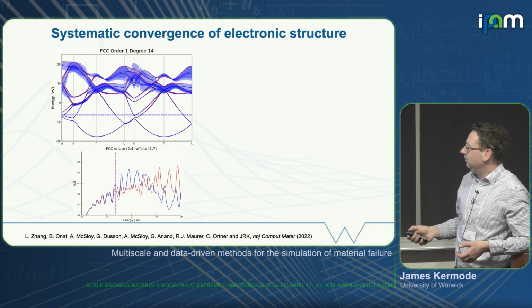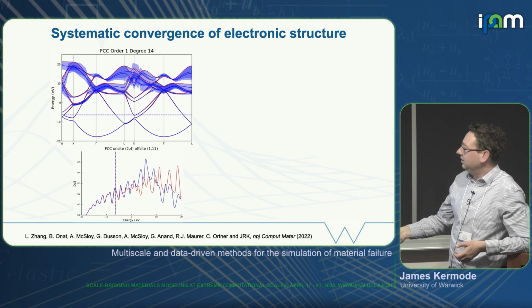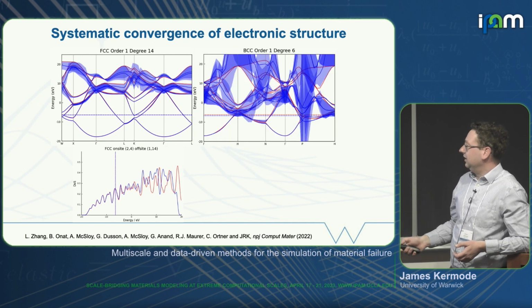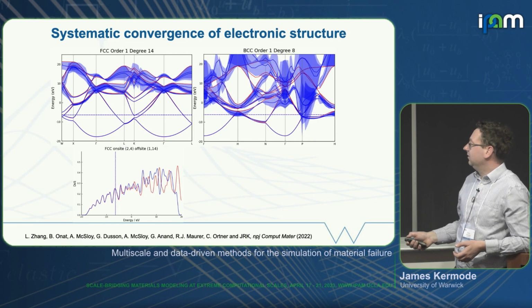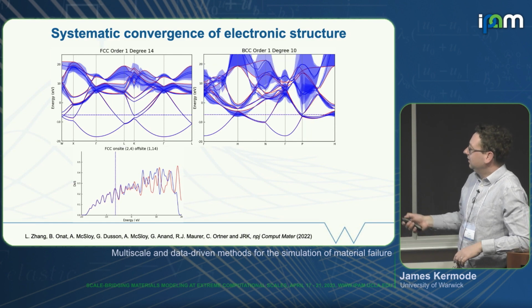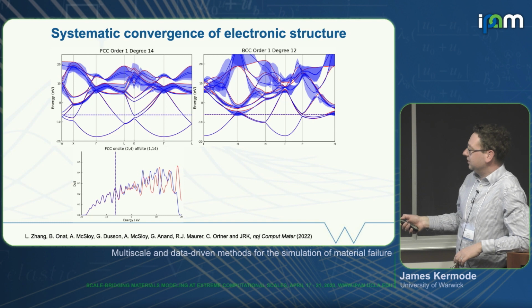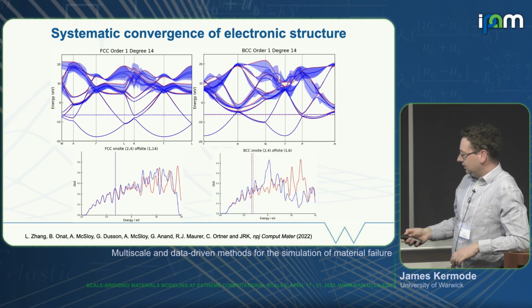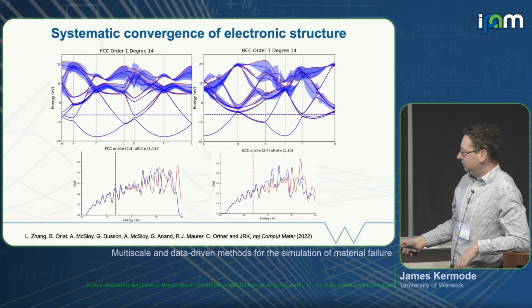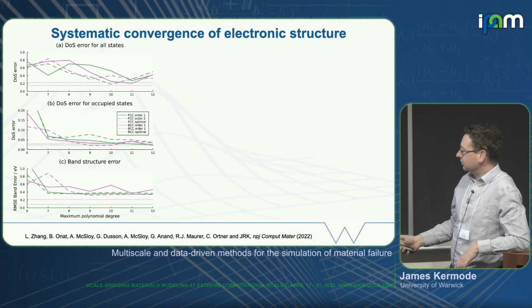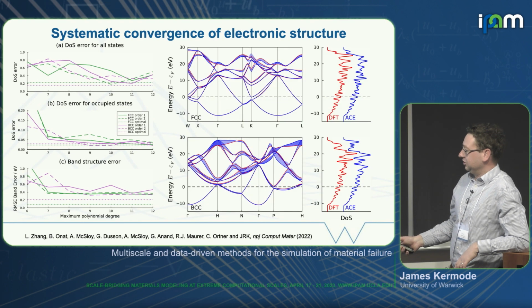And you can see both the band structure, certainly for the occupied parts of the band diagram, and also the density of states, converge quite nicely as we increase the size of the basis set. Same thing for BCC, maybe not quite as accurate, but again, up to the Fermi level, it's well described. And similarly for the density of states, up to the occupied part of the spectrum. This is just showing the same thing.